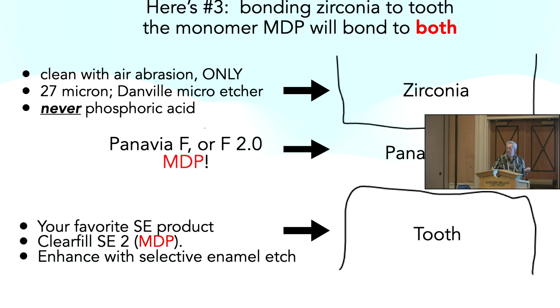The big bugaboo with zirconia is that you cannot clean it with phosphoric acid. That is the technique for an etchable ceramic. Zirconia is not etchable, okay? Zirconia has a phosphate binding site to it. When you wash it with phosphoric acid, you're now contaminating those phosphate binding sites with phosphoric acid. And then when you use anything else on it, nothing will stick.